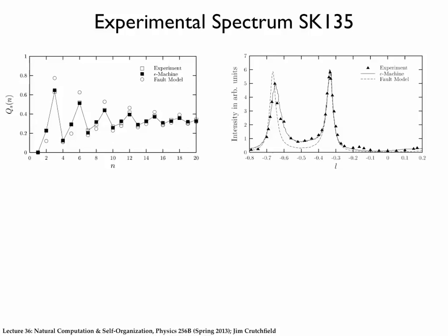Aha. So we see something right here. This is about at a third, and this is about minus a third. So we really want to think about period 3. What has period 3? 3C, exactly. And we see both of these peaks. So naively, when you look at this value, you say, well, this looks like a crystal that half of it maybe is 3C minus, and this would be 3C plus. So it looks like I have that, and I have a lot of disorder between them that is somehow connecting them.